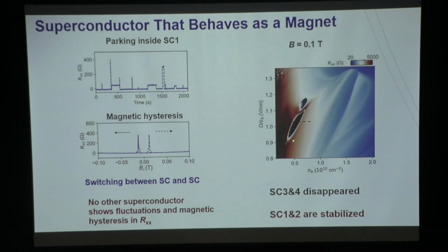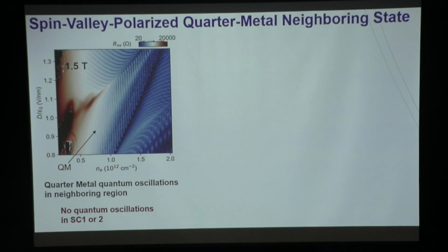So when you apply an out-of-plane field, say 0.1 Tesla, you get to this saturated regime, you're far above the coercive field. What you find is that instead of being killed, SC1 and SC2 actually got stabilized. All the fluctuations that we were talking about are simply gone. The magnetic field helps the superconductor to be stabilized. And that also agrees with what you would expect for a magnet. Okay?